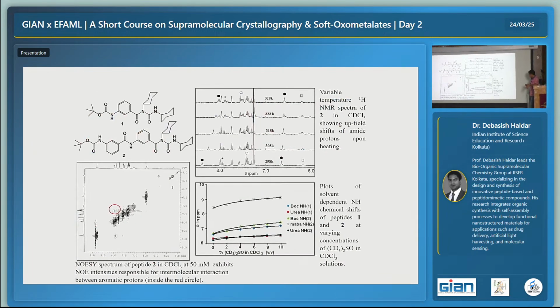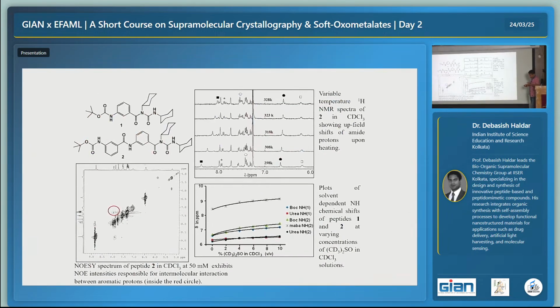And then we developed a larger version of the foldamer, with 2 meta-aminobenzoic acids in the chain. From solution state studies with NMR, 2D NMR, temperature dependent NMR, and solvent titration of DMSO-d6 in CDCl3, we figured out that the two compounds have different folding patterns in solution.